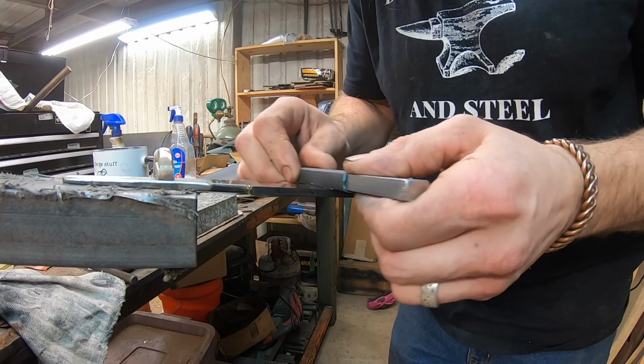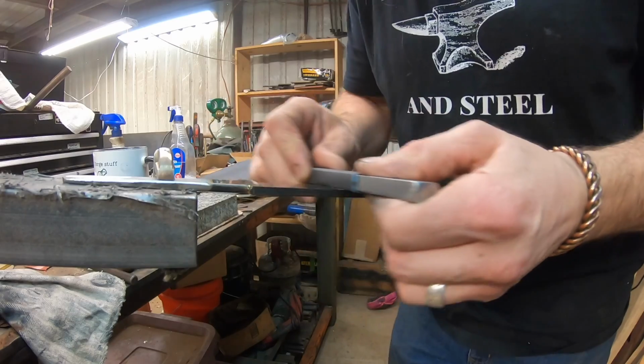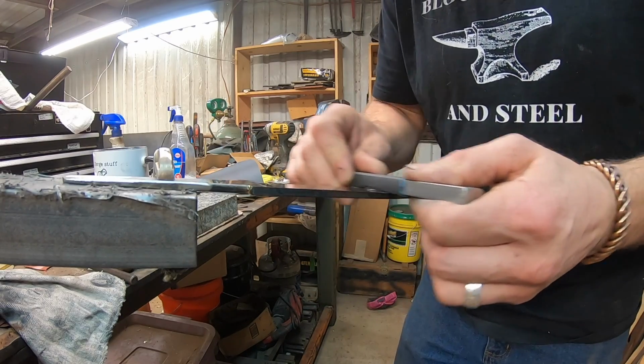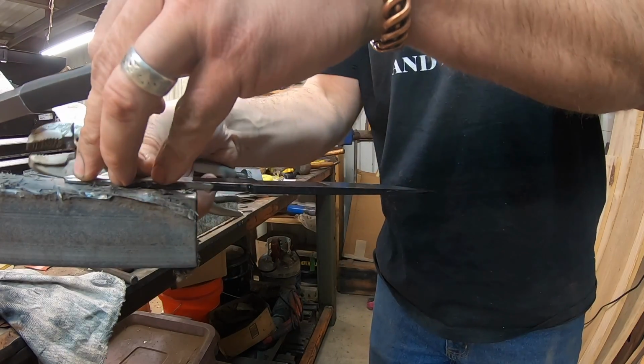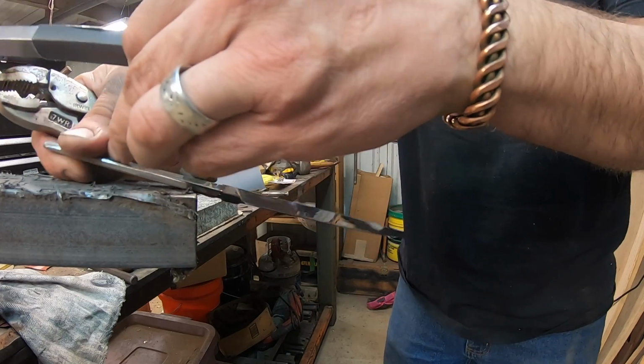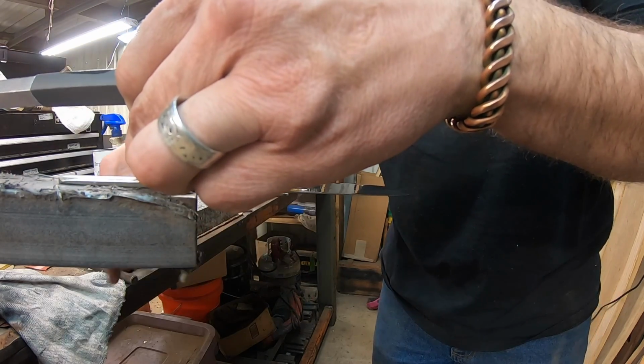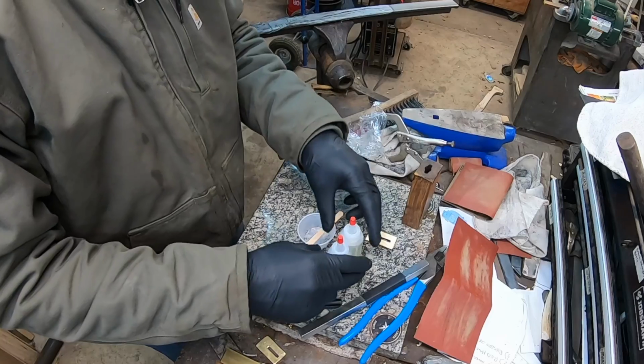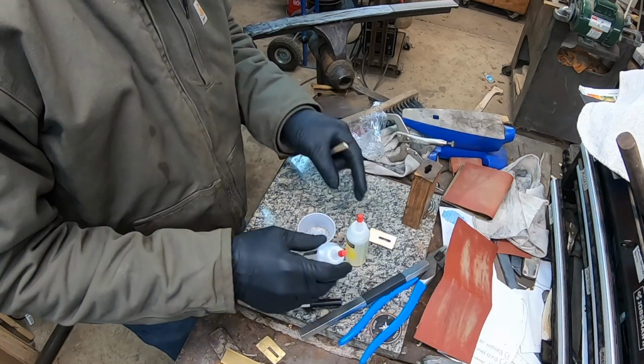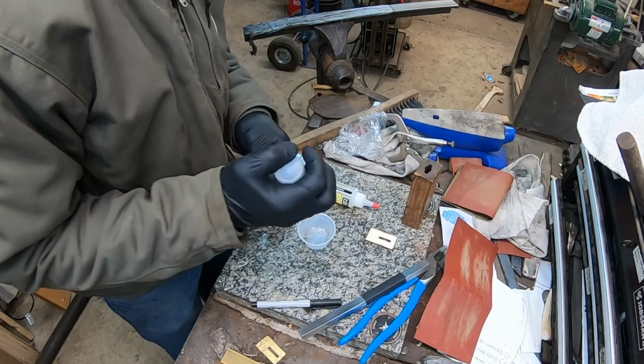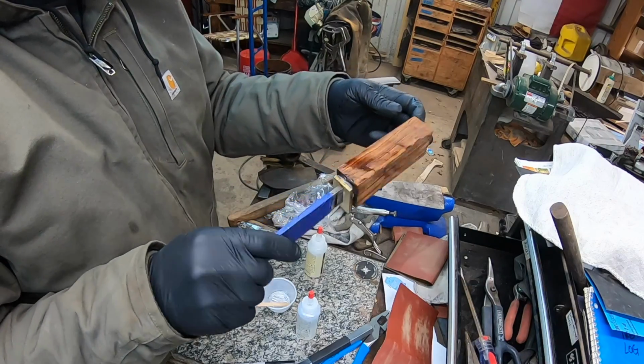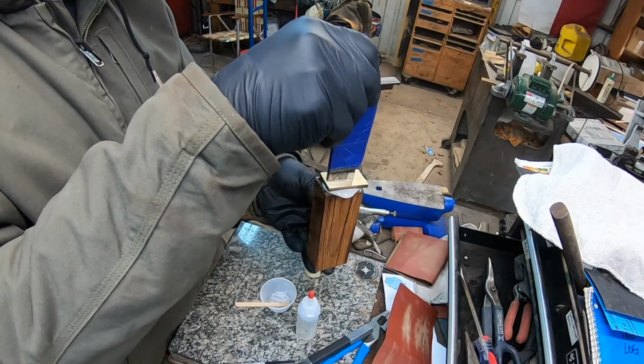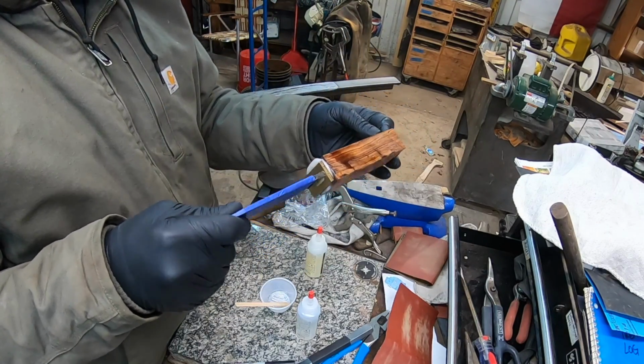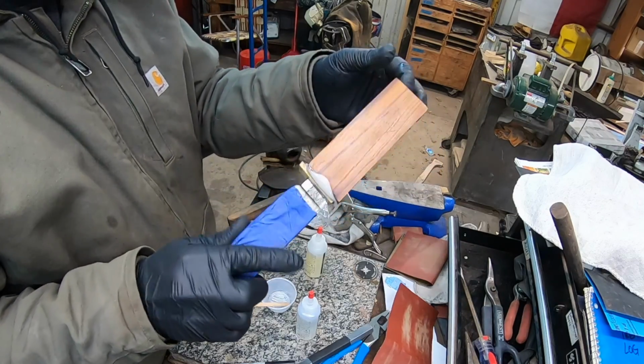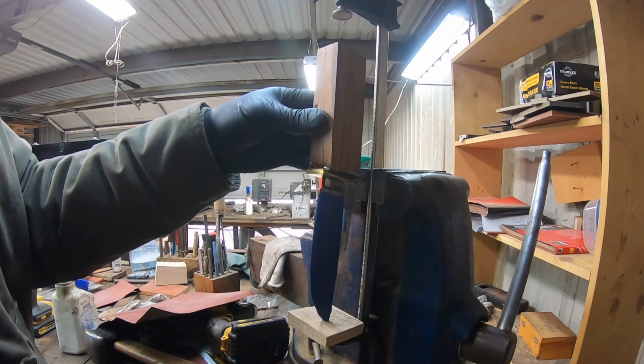Into the ferric chloride, we've got to etch this blade to bring out the pattern that we have. Hopefully it's going to show up nicely and give us a good pattern on our blade. I've got to clean the oxides off in between every time I take it out of the etch, multiple times. We've got a piece of desert ironwood to fit up for the handle, and we'll get epoxy set up in there and everything together nice and tightly.